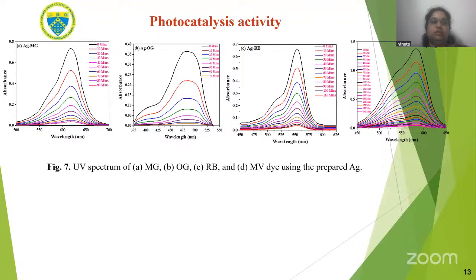The photodegradation of malachite green, orange G, rhodamine B, and methyl violet dyes by the synthesized silver nanoparticles under a UV light source was evaluated. These experiments were conducted at room temperature using a UV lamp. Dye concentration was monitored over time by measuring the maximum wavelength at constant 10 minute intervals, revealing a significant decrease as the reactions progressed. Here we have used the same dye concentration and the same volume for all the dyes.